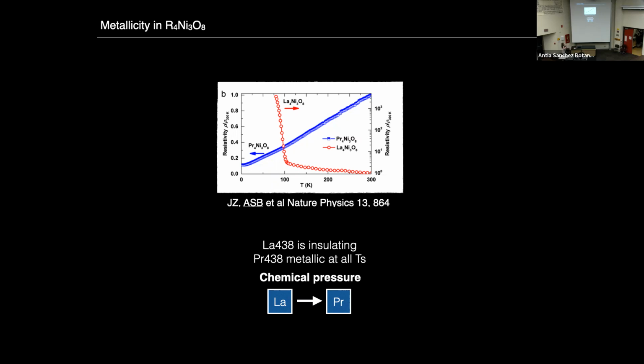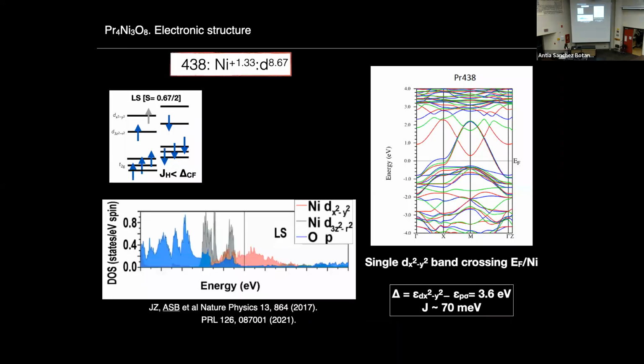So the lanthanum material actually wants to charge order, and that's the reason why it behaves in this way. Then through a chemical pressure effect, the praseodymium material doesn't charge order, and it's pretty happy just being in a metallic state. So I'm not going to focus on the lanthanum material today, even though that's very interesting in and of itself. Let me just, though, tell you a few words about the praseodymium counterpart, which is, if you want, the more cuprate-like of the two.